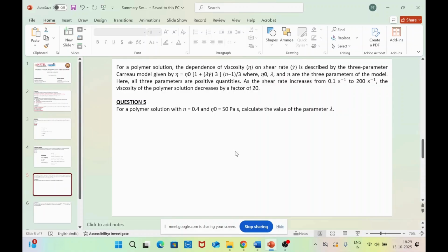As we have seen even in the last class, the Carreau-Yasuda model can be reduced to a three parameter model by applying some constraints. All the three parameters here are positive quantities. As the shear rate increases from 0.1 second inverse to 200 second inverse, the viscosity of the polymer solution decreases by a factor of 20. It is also given that the value of n is 0.4 and eta naught is 50 Pascal, that is your zero shear viscosity. Now based on these data, we are asked to calculate the value of lambda.